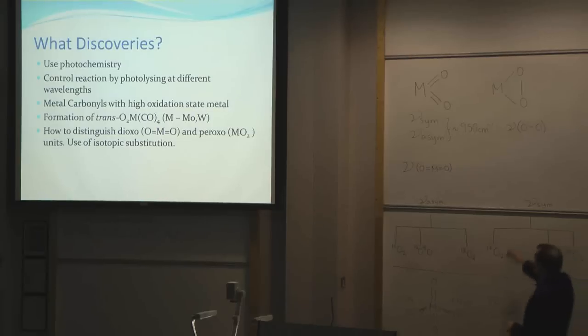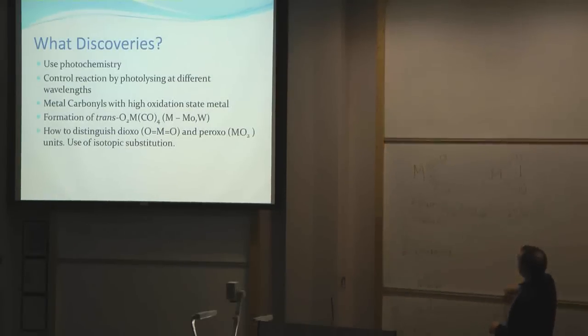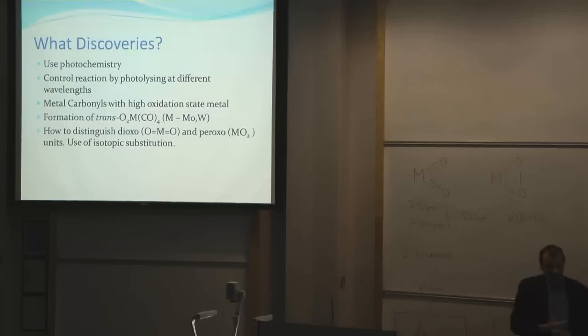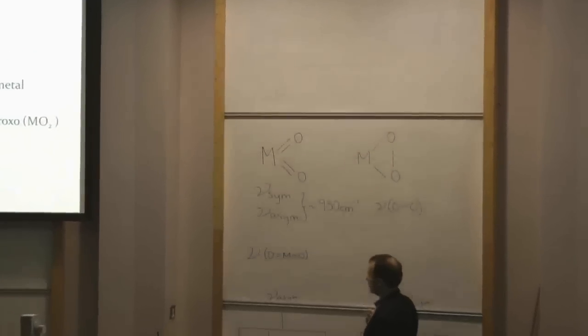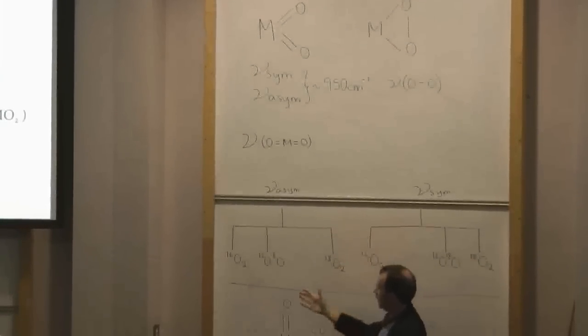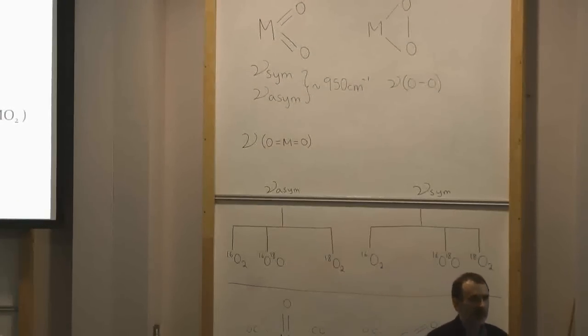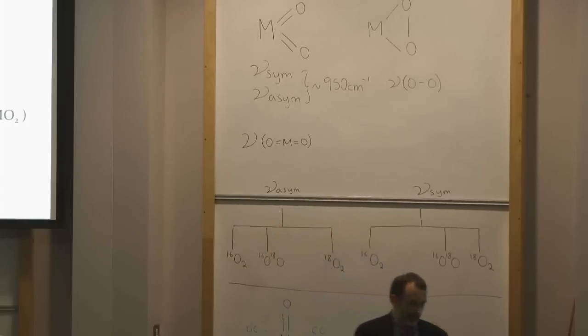One of the little problems, which is quite interesting, is that if you have a unit like this, a dioxo unit, where the oxygen-oxygen bond is broken, the infrared stretch actually goes very close to the oxygen-oxygen stretch of one where the oxygen molecule isn't broken. And it's not always easy to distinguish the two. The classical way of distinguishing these was to substitute the molecule with a mixture that includes the mixed isotope 16O-18O. The reason that that can distinguish the two is that if you have the dioxo unit, the one that's up here on the left-hand side, you have a symmetric and an asymmetric stretch.